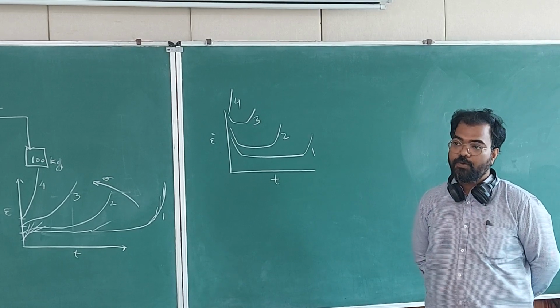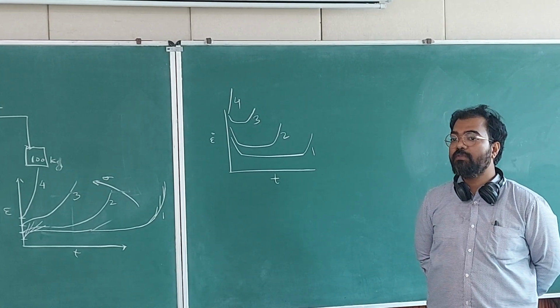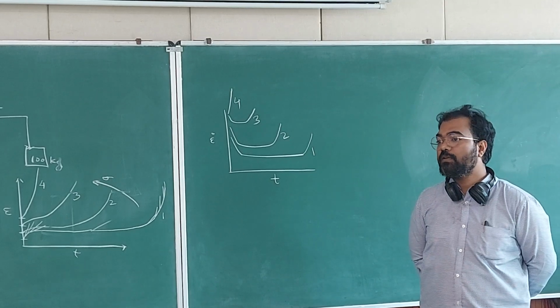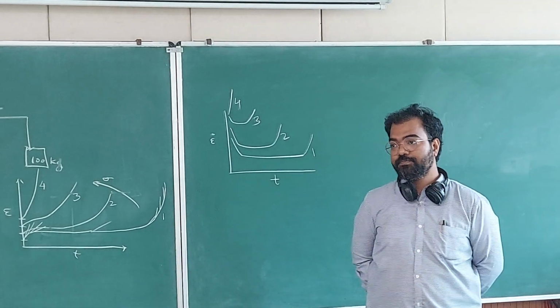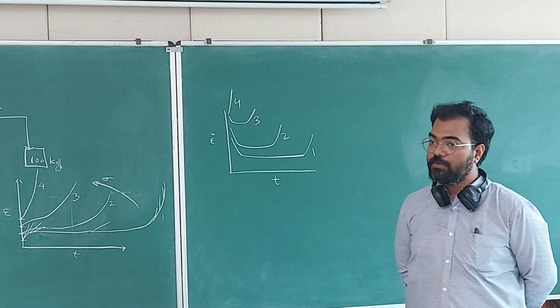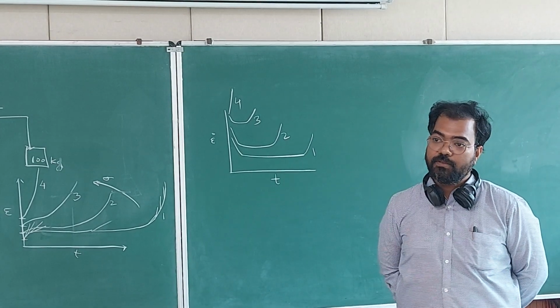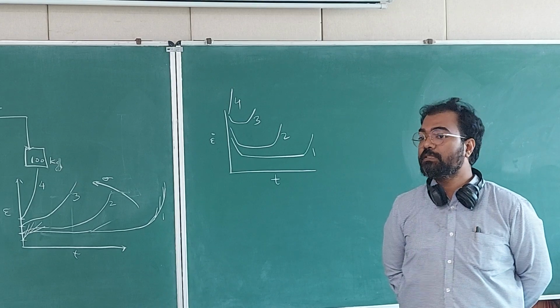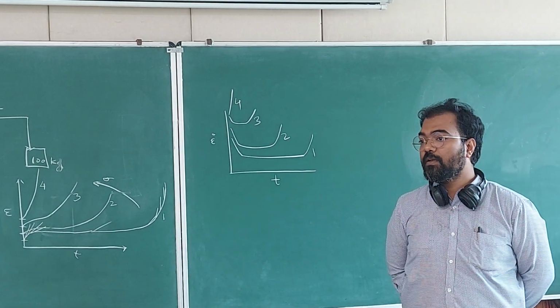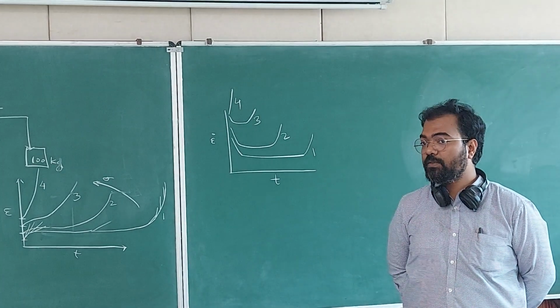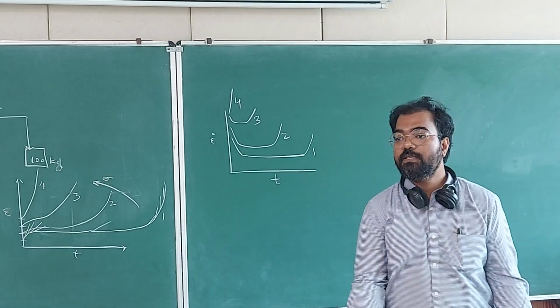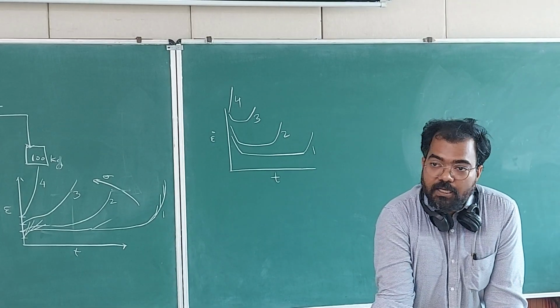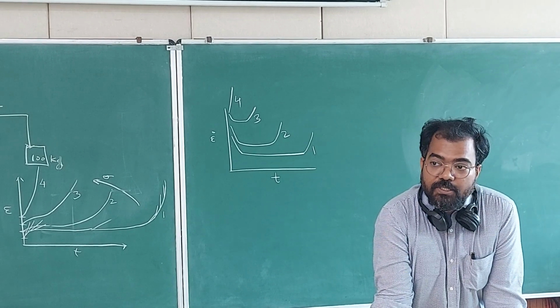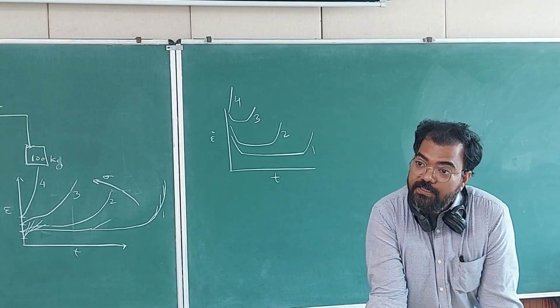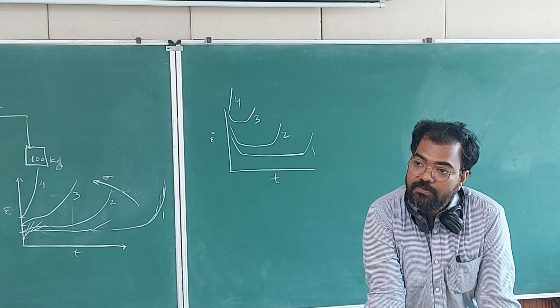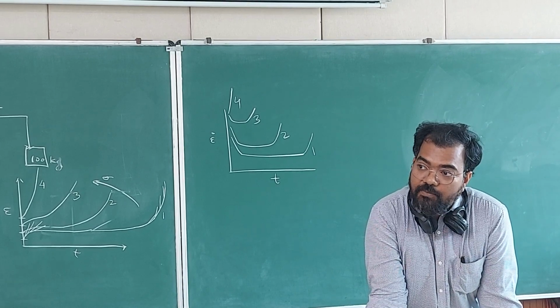Okay. So effect of climb is not very high at smaller values of time, because that's a diffusion controlled process. So that effect will become significantly larger either you decrease the stress, or you increase the time, or you increase the temperature. Not necessarily a thumb rule. If you increase the temperature to a very high value, then the mechanism will change. Instead of climb, something else will start happening, and climb will be suppressed